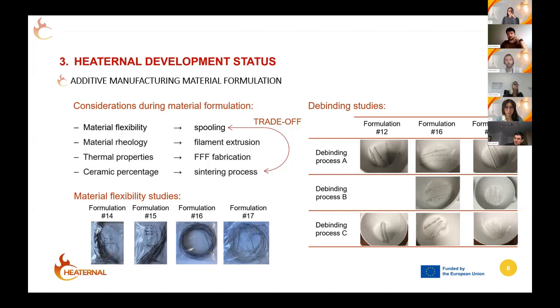However, as noted here, this last consideration is a little bit contradictory with the first one, in which we look for material flexibility. So as we increase the ceramic percentage, for sure, the material flexibility will decrease. And this is addressed by the use of several additives in the formulation. As you can see, the material formulation takes into account all those previous steps that I was just explaining in the last slide, which makes it even more challenging, okay?